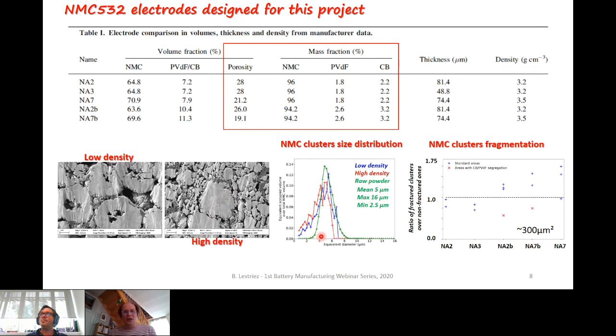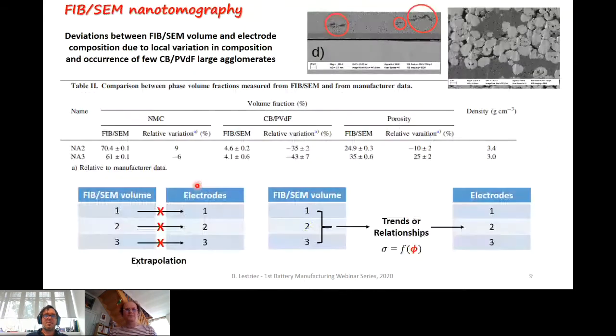So you see that the mean particle size is decreased a little bit. What can be observed is an increase of the smaller particles. And this fragmentation is really significant because when you quantify the ratio of the fractured clusters over the non-fractured ones, you see that more than half of the clusters have been fractured. So this is something to input in the models to take this fragmentation into consideration, because you will see it has a significant influence on the ionic transport properties and then on performance.